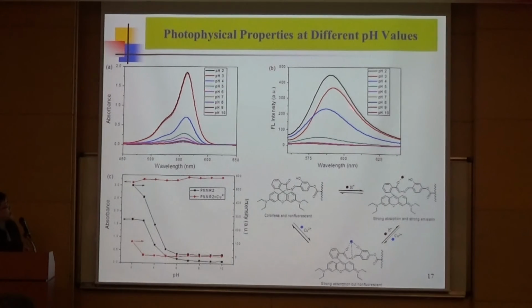And from the UV and PL spectra of our PNR2 nanofiber at different pH values, you can see the turn-on of absorption and the turn-on of fluorescence at a pH value lower than 4. And from the plot of absorbance and fluorescence intensity as a function of pH value before and after addition of copper ion, you can see that after binding with copper ion, the absorbance can be turned on even at high pH value. However, the fluorescence was quenched after the addition of copper ion.